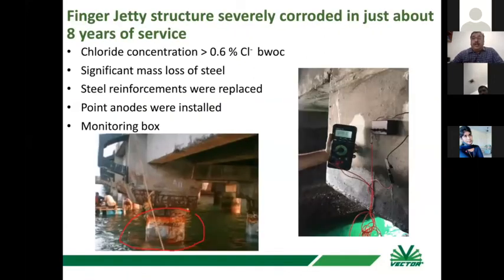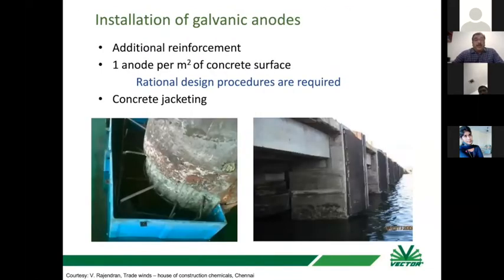And they found out that the chloride concentration was very high and there was significant mass loss of steel, and reinforcement were supposed to replace. So they just added point anodes here. The design was done now with experience, we had further rationalized the design, but the design done was 1 unit per meter square, and even a monitoring box was installed. And this is how the work was done.